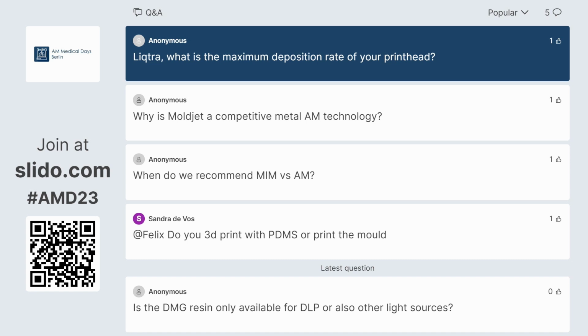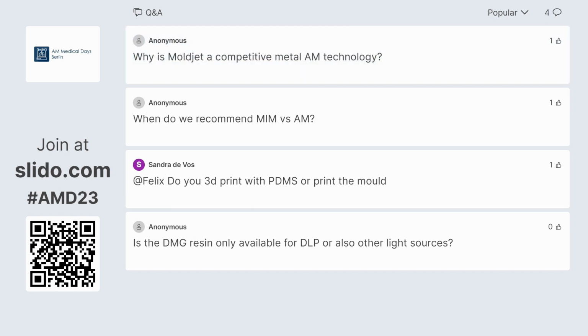But the problem there is you need the right part to perform on that level, because the part needs to be huge for the material to have enough time to cool down before you go there the next time. But rates up to 100, that's totally fine on regular parts that we see here.